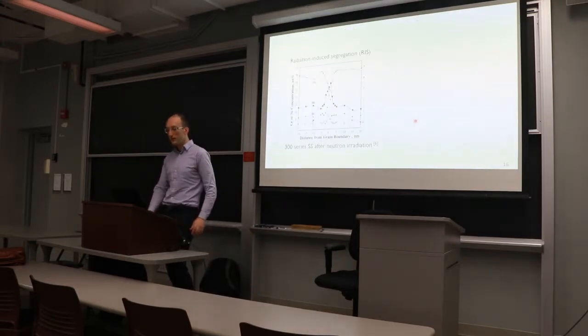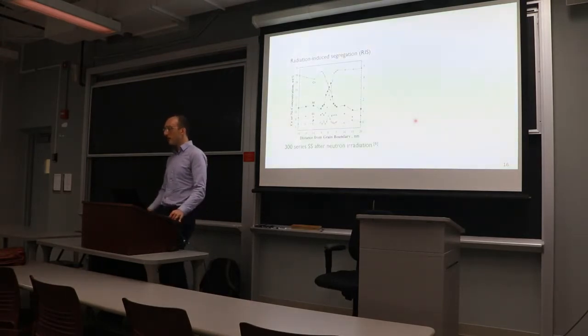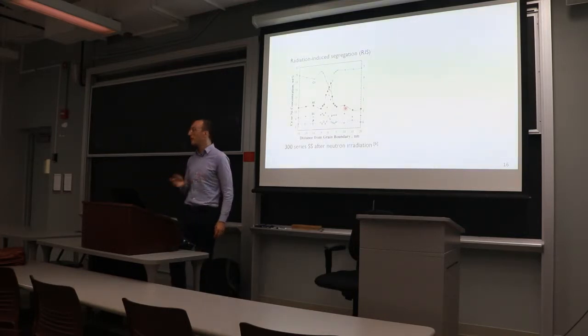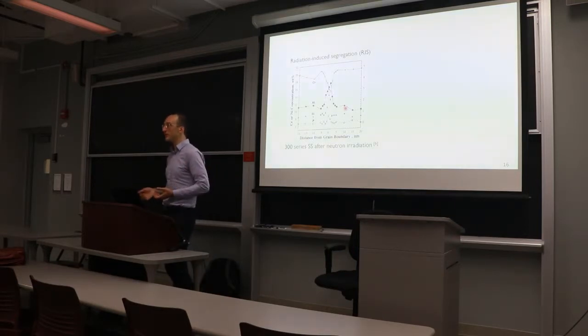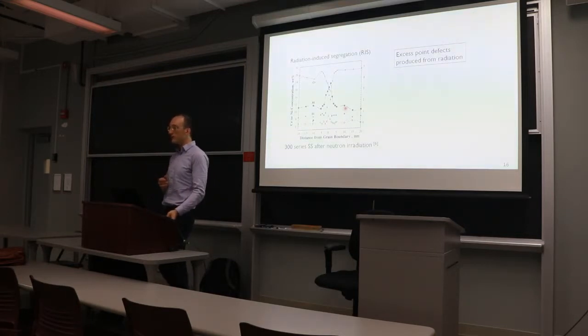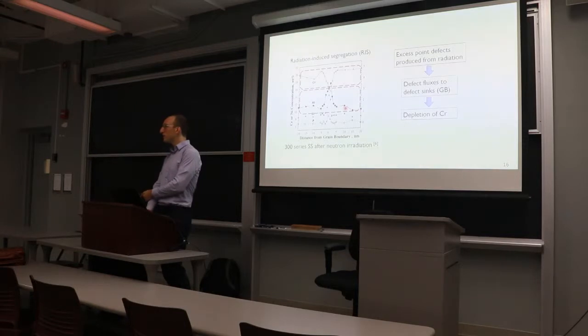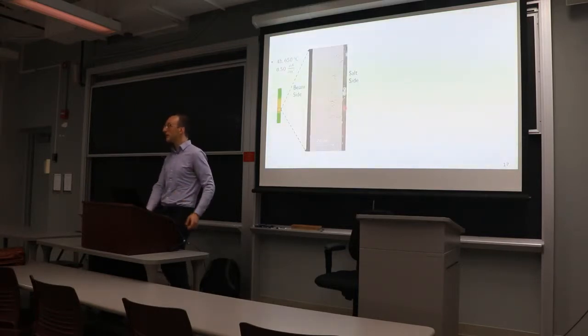And the mechanism we're proposing is classic radiation-induced segregation. So this is a TEM line scan showing chromium depletion and nickel enrichment on a stainless steel grain boundary. This is what makes your stainless not stainless in light water reactors. And this is bad. But in a fluoride-cooled salt reactor, there's no protective oxide, there's no passivation, there's no such thing as stainless. And so creating point defects from radiation would preferentially pull the chromium away from the free surface and push the nickel towards the free surface, depleting chrome from where the salt can see it, and causes this decelerated corrosion.